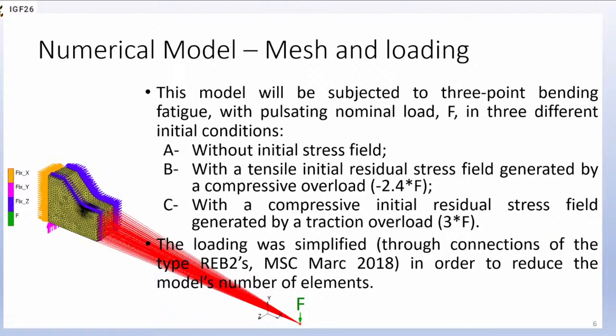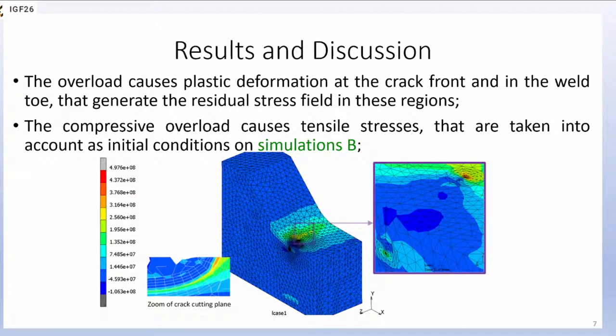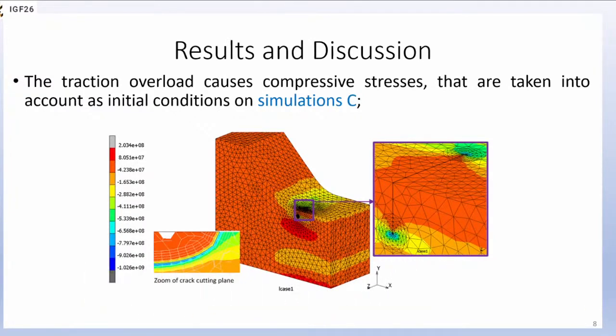This model will be subject to three-point bending fatigue with pulsating nominal load in three different initial conditions. A, without initial stress field. B, with the tensile initial residual stress field generated by a compressive overload. C, with a compressive initial residual stress field generated by a traction overload. The overload causes plastic deformation at the crack front and in the weld toe that generate the residual stress field in these regions. The compressive overload causes tensile stresses that are taken into account as initial conditions on simulation B. The traction overload causes compressive stresses that are taken into account as initial conditions on simulation C.